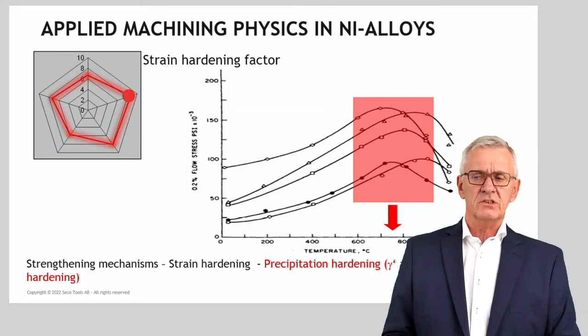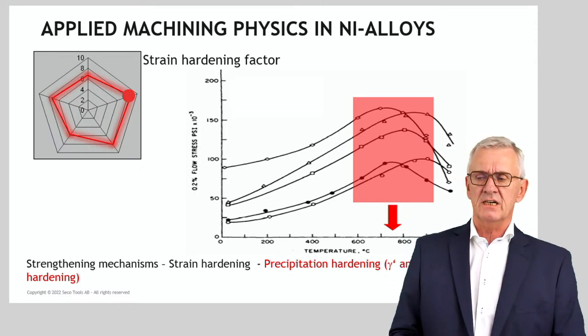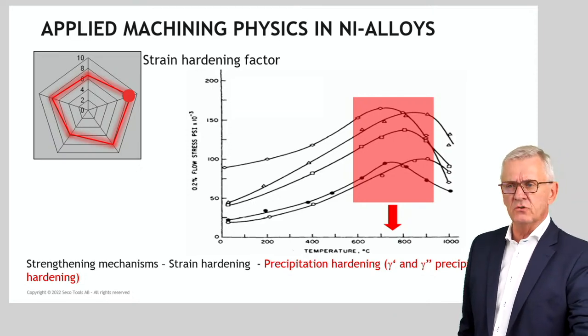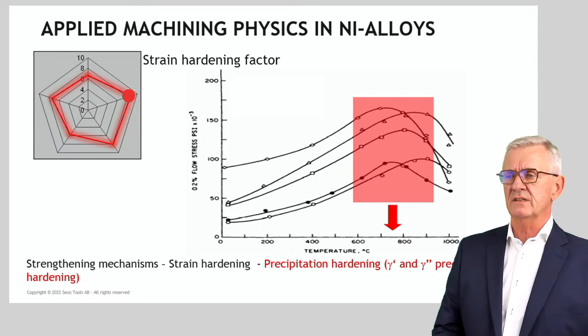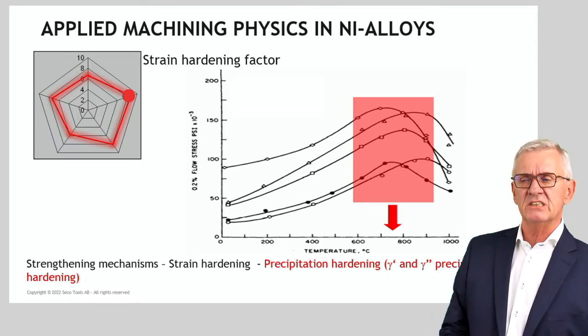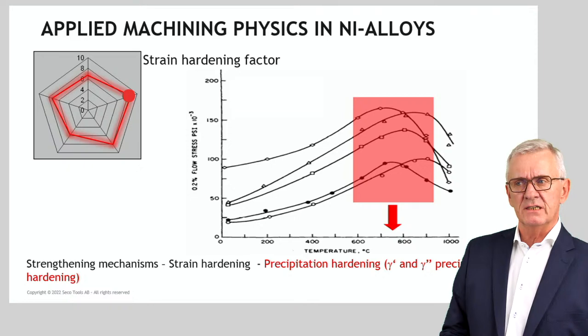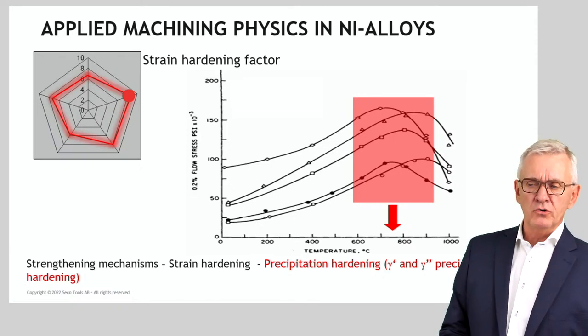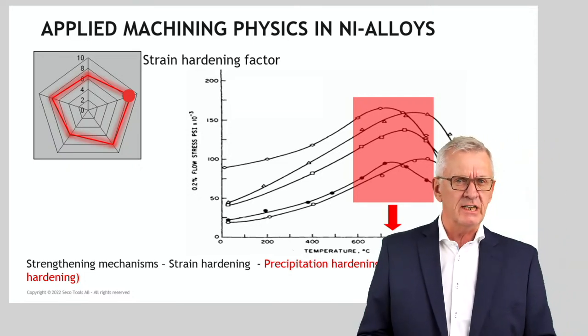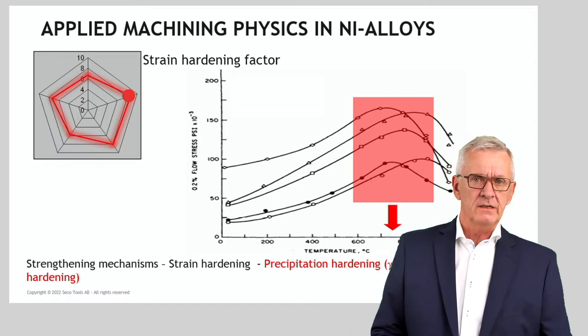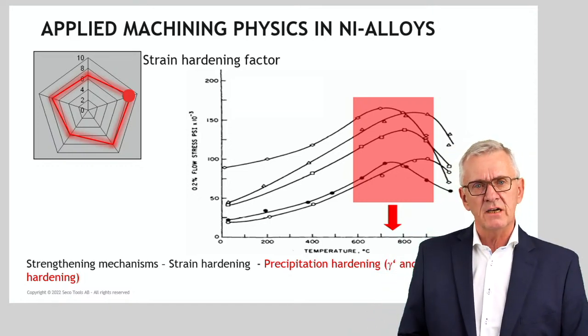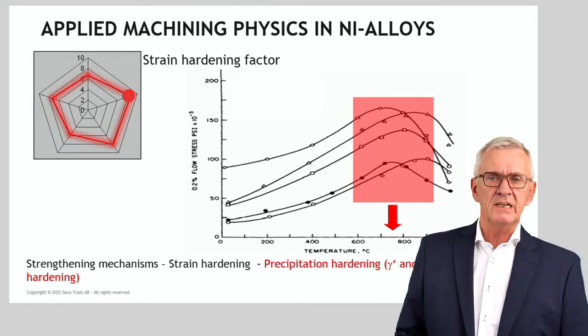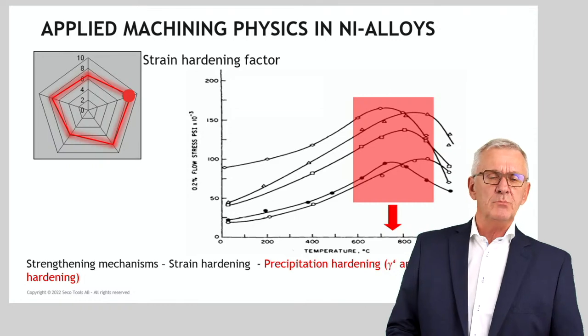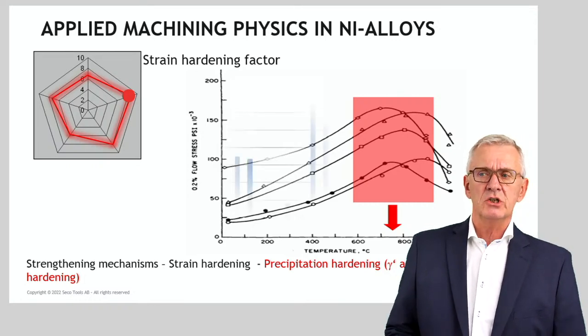Talking about strain hardening factors, a little footnote, but very important, is that we have to be aware that in nickel-based alloys, there is also precipitation hardening taking place. Precipitation hardening, I'm not going to try to explain the metallurgical phenomenon here. We don't have the time for that. But let me say precipitation hardening is that the material is hardening under the influence of temperature and strain. And you know, precipitation hardening, that's what the graph tries to show us, takes place for most materials somewhere around the temperature of 800-900 degrees Celsius. And life is not fair. Because, you know, the typical cutting temperature is 800-900 degrees Celsius. So it could well be that next to strain hardening, while you do machining, you also get precipitation hardening of the surface. And that is a double-up situation.